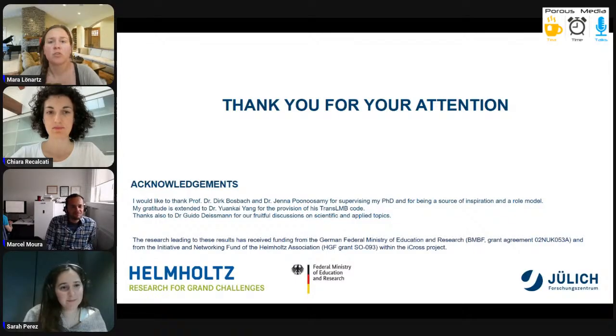Okay. It was just limited, because for me it would have been also interesting to leave the experiment running longer to see what happens with the critical effective diffusivity. So, for example, we could have changed the solution back to a normal one to see how water is now diffusing and where the deuterium is going. But the PDMS is also degrading after a while.